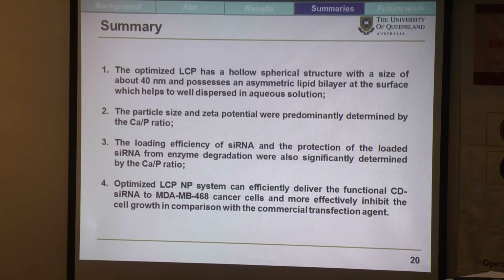This is a summary of our current work. We have successfully synthesized the LCP nanoparticle with a size of about 40 nanometers, which has an asymmetric lipid bilayer and selective charge. The particle size and the zeta potential were predominantly determined by the calcium to phosphate ratio. More interestingly, the loading efficiency of the siRNA and the protection of the loaded siRNA provided by the LCP nanoparticles were also significantly determined by the calcium to phosphate ratio. And our in vitro tests also suggest that the LCP nanoparticles we synthesized can efficiently deliver siRNA to the MDA-MB468 cancer cells and more efficiently inhibit the cell growth compared to the commercial transfection agent.